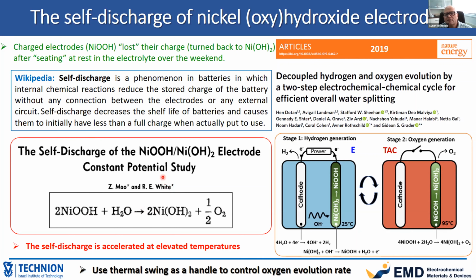And this led to the idea of what we call ETAC water splitting. ETAC stands for electrochemical, that is the stage where we produce hydrogen, and thermally activated chemical, that's the stage where we produce oxygen. So it's a two-stage process where first we put electricity between a cathode and a nickel hydroxide anode, such that the cathode produces hydrogen and the anode doesn't produce oxygen. Instead, it is being charged from nickel hydroxide to nickel oxyhydroxide. We do that as long as we have capacity before this electrode would start to evolve oxygen.